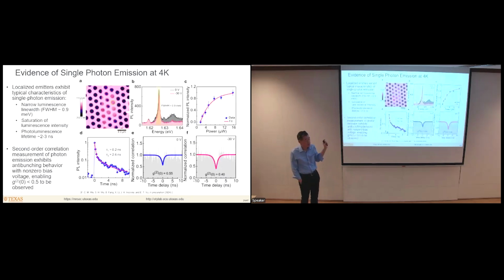If we look more specifically at what are generally considered to be the signatures of single photon emission in these materials, we see the following. These are measurements from this region of one of the samples over here, and specifically from this particular location. If we look at one of these localized emitter peaks, you can see that it has a very narrow line width, a little under 1 meV in this case, which is in the range that is generally required. We see that as we increase the excitation power for the photoluminescence measurement, there's a saturation in the luminescence intensity, which is also a signature of single photon emission. And then the lifetime that we observe is in the range of 2 or 3 nanoseconds, which is also about what you would want to see.